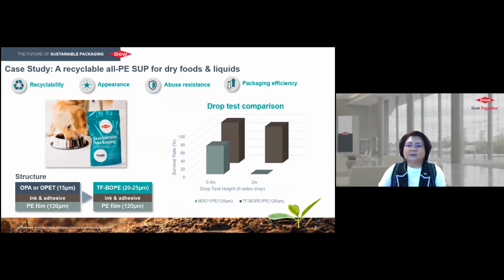So let's continue from the previous slide. Here, let's look at the drop test of the pouches, TFBOPE laminated solution, and the MDO laminated solution. The MDO-based pouches able to survive 0.5 meter of drop height at 50% of survival rate, while the TFBOPE based pouches has 100% survivable rate in cumulative of 6 sides drop tests. When we increase the height to 2 meter, MDO-based pouches unable to survive the drop test, whereas the TFBOPE-based pouches can still pass. This clearly demonstrates the difference performance when the same PE lamination film was laminated to MDO or TFBOPE film replacement substrates, demonstrating the unique performance of TFBOPE films.